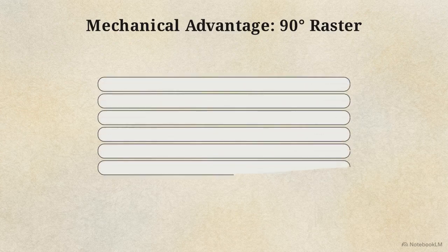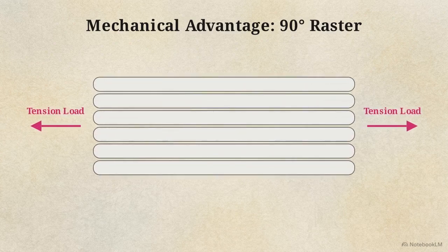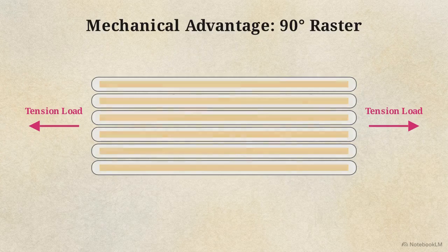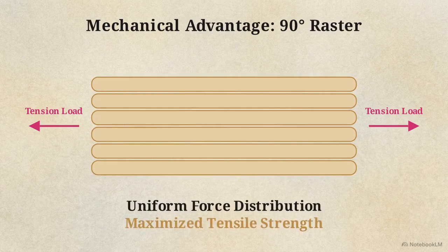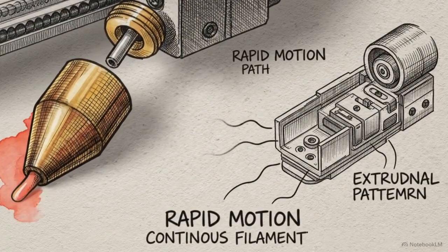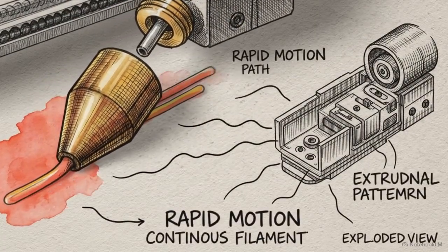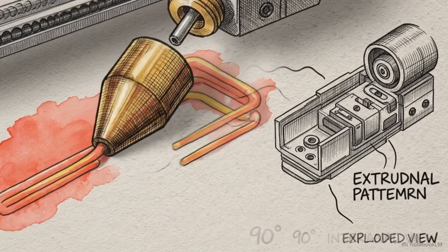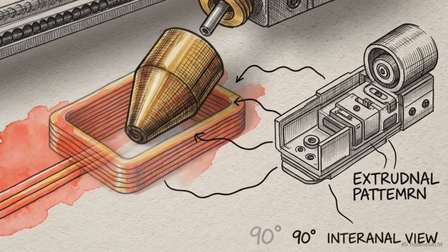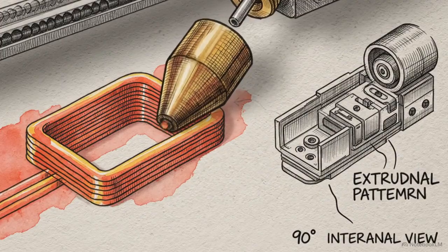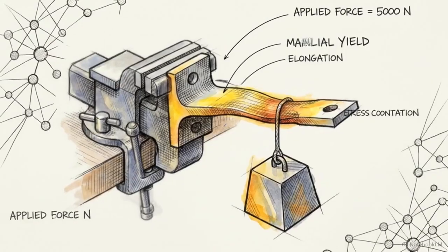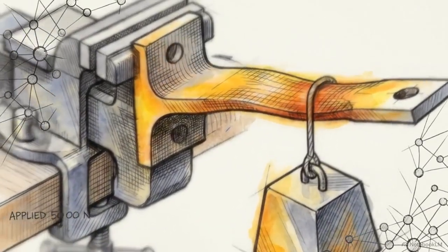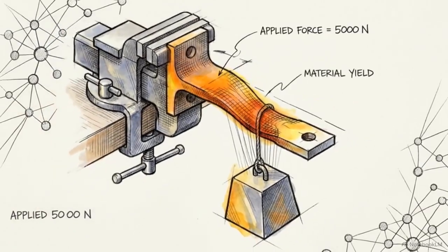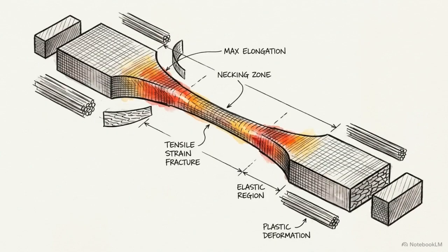A 90-degree angle aligns the continuous, unbroken lines of extruded plastic parallel to the tension load, optimizing the distribution of force along the length of the fibers. When engineering a polymer for pure tensile strength, toolpath alignment and internal mass density are the primary microstructural levers. Thermal parameters are strictly secondary. Maximizing rigid strength is only half the engineering equation. Certain parts need to yield and stretch before snapping. We have to pivot to measuring a part's elongation at break, or its ductility.